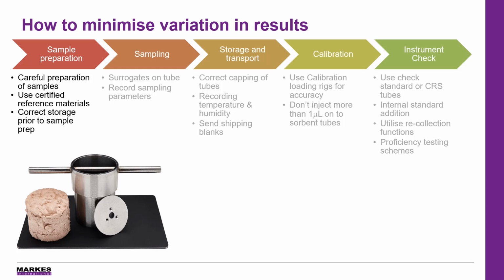When running any analysis, there are a few things that can be done to minimize the variability in the sampling and analysis to ensure more confidence in our results. For example, when using the microchamber, careful preparation of samples, using gloves, make sure samples are cut with clean tools. If samples are stored prior to use, then ensure they're packaged carefully. There are standard methods which outline these parameters depending on the material. So if you'd like any details of these, please reach out and we can share those.